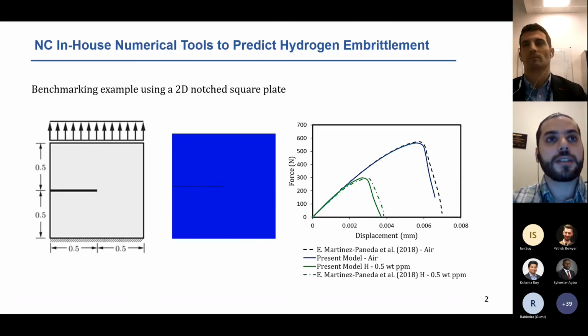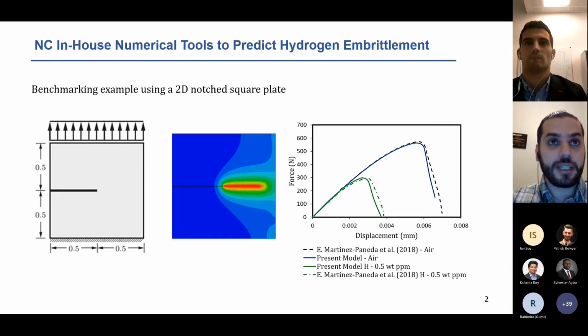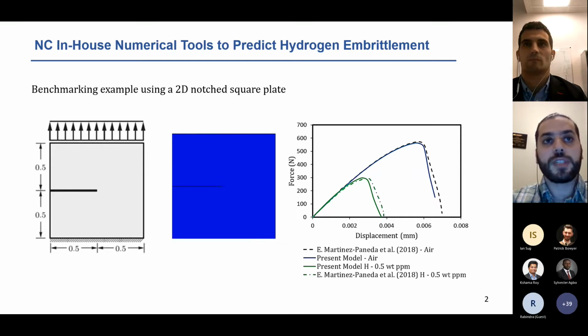The figure on the left shows the plate, which is fixed at the bottom and pulled from the top, and the video in the center shows the initiation and evolution of the damage, and the right figure presents the force displacement curve for scenario with no hydrogen, which is the blue curve, and the one with 0.5 ppm hydrogen concentration, which is the green curve. As you can see, 0.5 ppm of hydrogen concentration leads to around 50% reduction in the load carrying capacity of the plate, which demonstrates the significant effect of hydrogen embrittlement in steel.